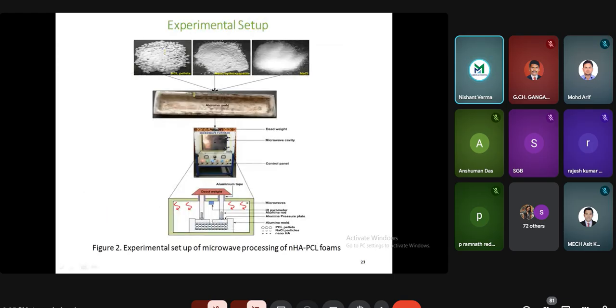How have we done this? Again, we have taken the alumina mold. Why have we taken the alumina mold? Because alumina is a microwave-transparent material, and it is thermally stable up to 800 to 900 degrees Celsius, while a polymer is stable only up to 150 or 200 degrees Celsius. And the second thing is that it allows the microwaves to pass.